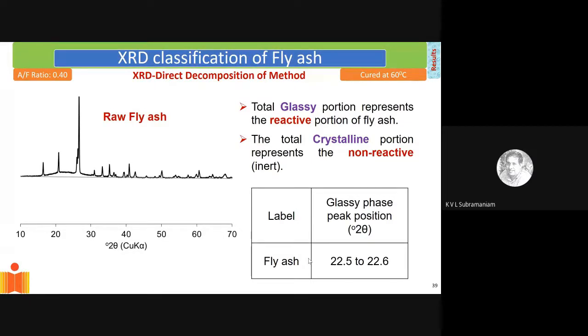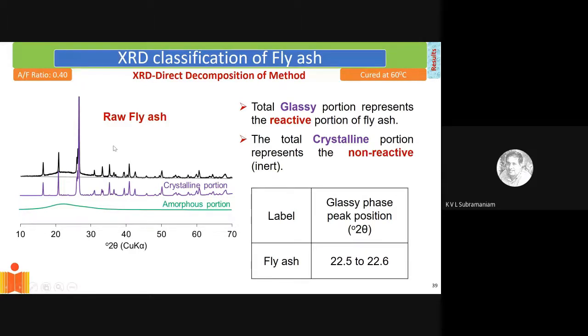And so if you do XRD, which is X-ray diffraction spectroscopy, one can learn to distinguish between the amorphous and the crystalline materials. If you look at an XRD signature for a raw fly ash, it would have all these peaks that show up. And the peaks are produced by crystalline materials that are present in the fly ash. So I can break up the XRD signature of the fly ash into two parts. One is these peaks, and the second is this background, this broad hump. That broad hump is the amorphous portion, because when you have amorphous material, X-ray diffraction does not produce well-defined peaks. It gives a very broad, diffuse hump.